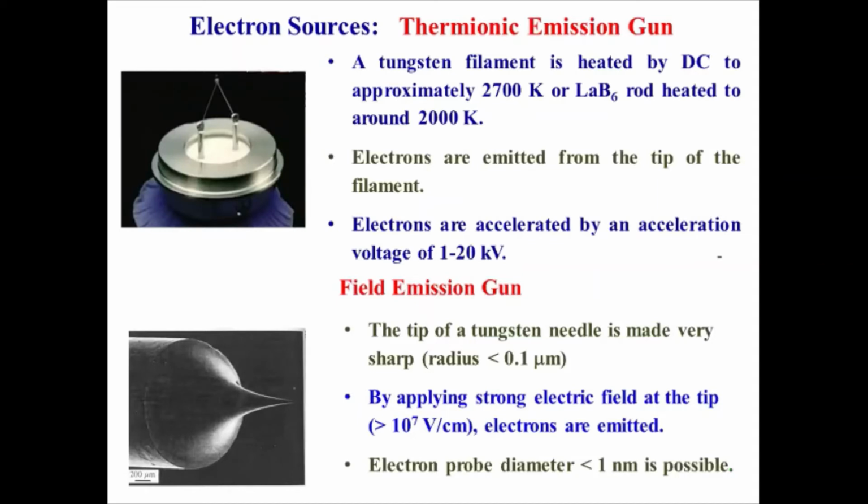Put it in a V-shaped structure, attach it to two metal electrodes, and when you apply a small potential difference between these two electrodes, there is a flow of current through the tiny wire, and due to Joule heating effect, the temperature of the wire rises, and at a particular temperature electron emission takes place.